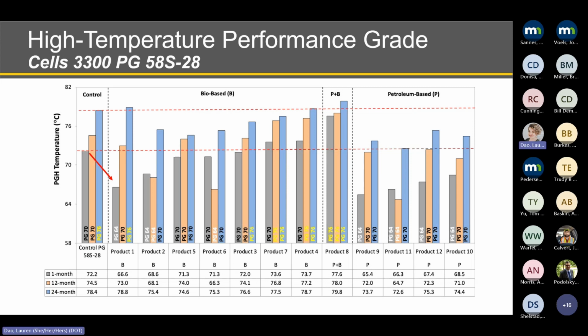It can be seen that, regardless of the category of the products being evaluated, we see a significant decrease for some products in the pass/fail temperature at the high end of the PG after 1 month of treatment application. However, what was observed after 1 month of the treatments being applied is not what remains after 24 months in the field. When considering the bio-based and the petroleum-based, you can see that the petroleum-based products resulted in much lower pass/fail temperature compared to the bio-based product, regardless of the field age interval.